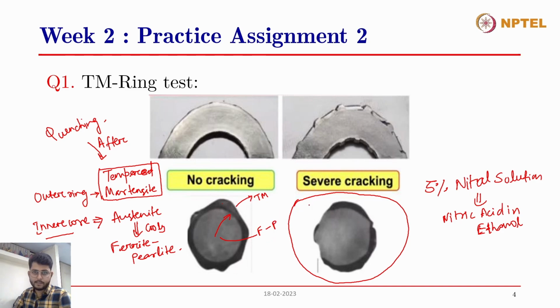The purpose of this test is to assess the quality of the manufacturing process. Over in the right rebar section, you can see that the ring is not uniform. There is some kind of etching at these locations, and at this location as well. The tempered martensite is also not uniform all around the ferrite-pearlite core, so this is not a good quality rebar. While the rebar on the left has a completely circular cross section of the ferrite-pearlite core, and the tempered martensite ring outside it is more or less uniform. So this is a good rebar, and this is what is done in quality assessment.